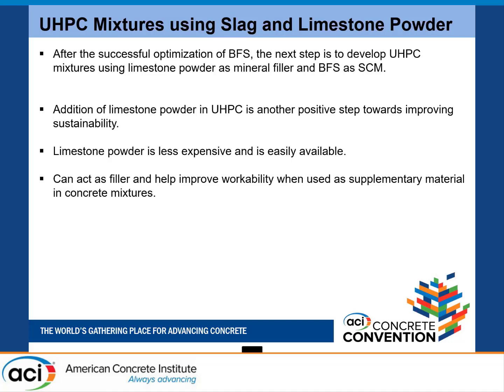Especially in a UHPC system, we are using about 1500 pounds per cubic yard of cementitious material with a very low water-cement ratio of 0.15. And typically we need 28% water for completing the hydration. We are 13% less than what we require. Therefore, not much hydration can go on, unlike conventional concrete. A lot of unused cementitious binders will be left and they will be acting as filler rather than binding material.